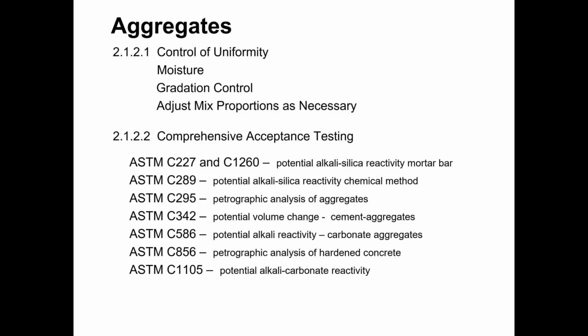All right, let's talk a little bit about aggregates. So we want to make sure that we're controlling certain aspects of our aggregates to ensure that we get the proper performance from those aggregates and we get consistent production of quality concrete. So the uniformity of our aggregate is with regard to the material that is being used, the geology within the aggregate. We want aggregates to generally come from the same geological formation so that we're not getting variation in the materials that make up the aggregate.